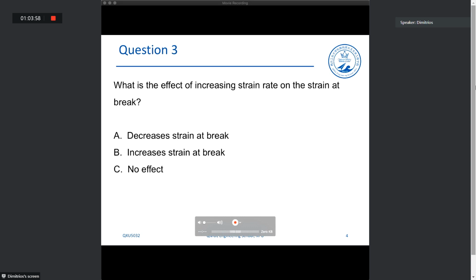Very well. The polymer group, 95% of the people said A. Check the materials. 92% of the people said A for the materials. Indeed, the effect of strain rate on the strain at break is that it decreases the strain at break. Also, the decrease of temperature has the same effect, because it makes the materials behave as glassy.